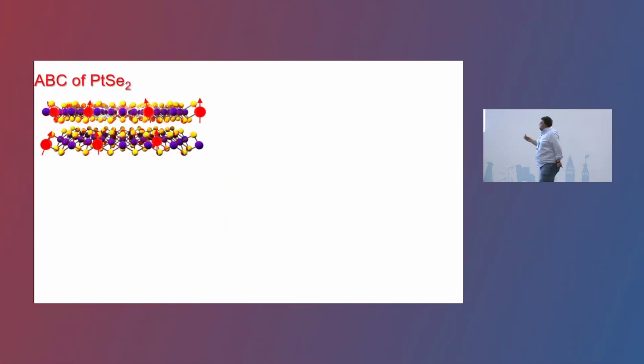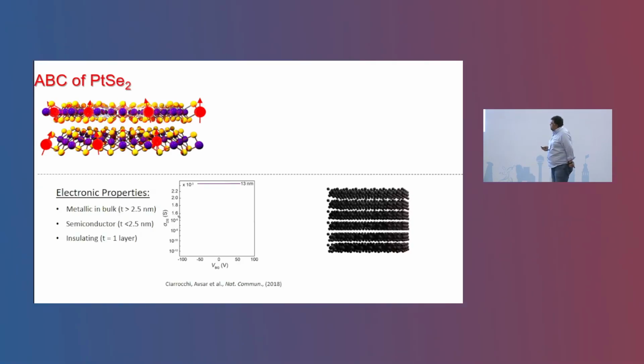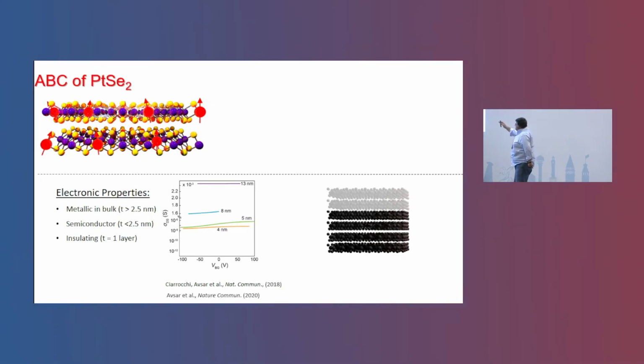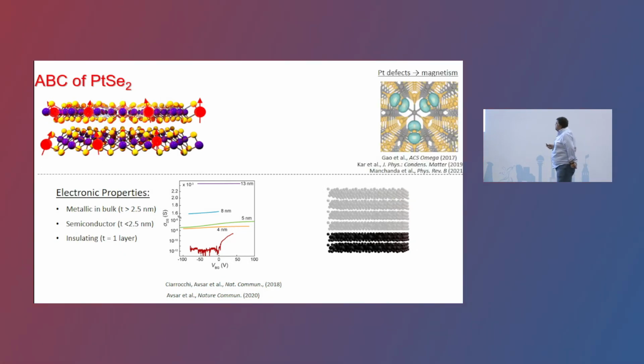So this is a material made of platinum sandwiched by selenium atoms. The material has very distinct electronic properties. It is a semi-metal once it has a thickness above 4 layers. Whenever you thin the material down, it becomes a semiconductor. And the material becomes a very good insulator once you reach the monolayer.